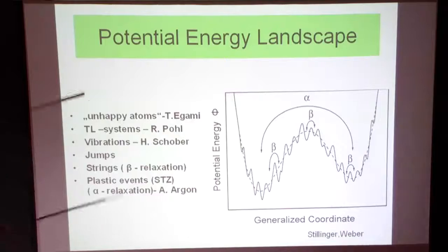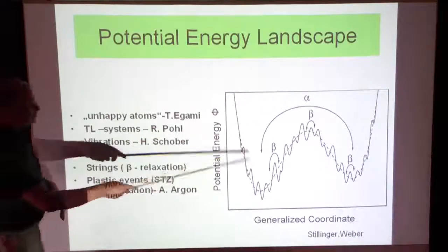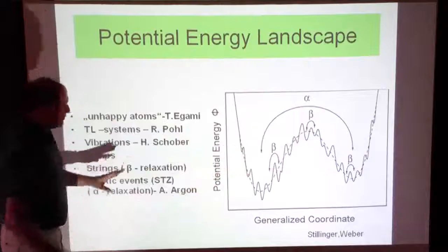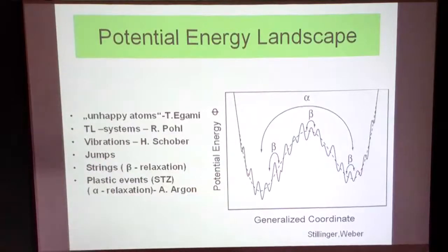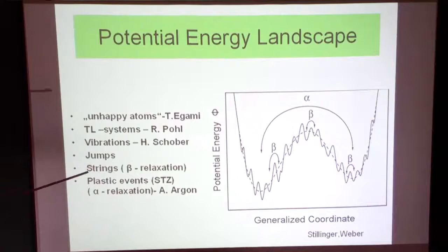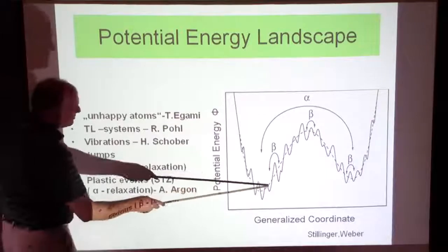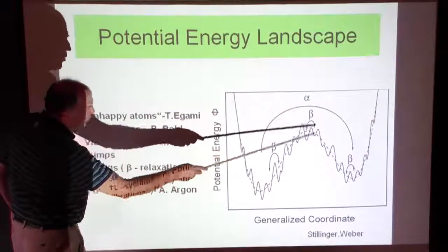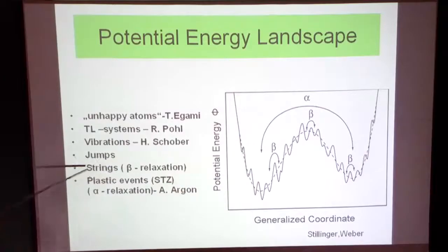Okay, so what did we learn? We learned that this configuration, which looks like a two-state model only, is actually manifold. So we have lots of different configurations in the metallic glass. The width of the distribution of the metabasins versus its depth is actually our number, because the depth is in the crystal ground state. And so we can now try to analyze what is going on locally for the different ones, for the strings, and then also for the avalanches.